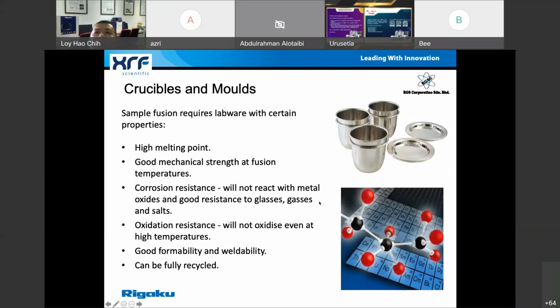any raw metals or steel, because any scratches or remaining steel or metals on your platinum surface, when you heat it up at 1000 degrees Celsius, will start to corrode or oxidize your crucibles, and slowly your crucibles will become dented and get a hole. Okay, so oxidation resistance: this will not easily oxidize even at 1000 degrees Celsius. Good formability and weldability, so it can be easily formed, and the good thing is it can be fully recycled.